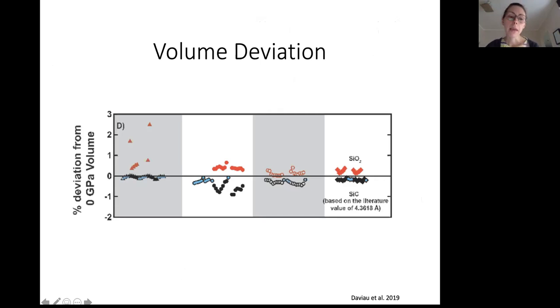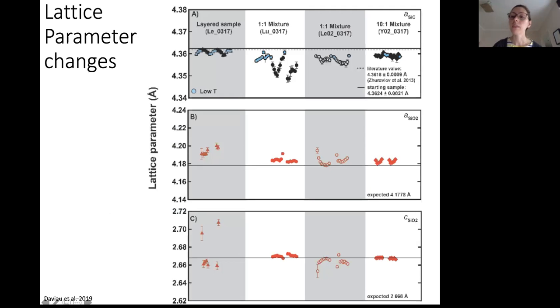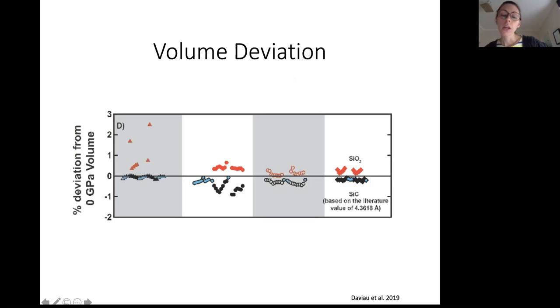So what this may mean, and how we interpret these results, is that when carbon comes out of silicon carbide, right, so at these hot temperatures, we're observing the appearance of carbon diamond. Some of this carbon, when it comes out, is decreasing the volume of silicon carbide, but some of it is being incorporated into silica, expanding the volume. And this is consistent with previous studies looking at carbon incorporation into silica, where they find that the largest change is in the A lattice parameter rather than the C lattice parameter. And so we may be seeing carbon incorporation into the silica.